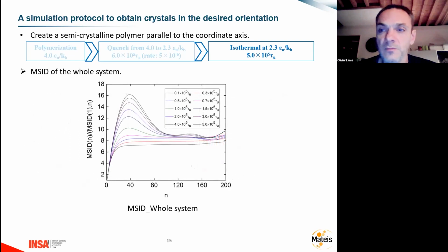So first of all, we use an indicator of the equilibrium, I would say, of the chain, which is the MSID, which is the mean square internal distance, which is the distance between 2 atoms inside the chain for any number of beads. And then normally the equilibrium is close to this black curve, which is an increase, and then a constant. It's an end-to-end distance.